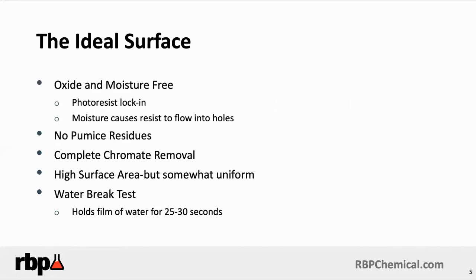Now, what is the ideal surface? The ideal surface to get good photoresist adhesion has got to be clean, right? Clean virgin surface, oxide-free, moisture-free, no residues left on the surface. We talked about chromate removal, and we're going to talk about how important it is. Chromate is what's put on the copper foil by the copper manufacturer to minimize or prevent oxidation when they ship you the copper. Well, that chromate has got to be removed. And where a lot of people make a mistake is they don't remove the chromate first, prior to going into some of the other aspects of the surface preparation process, whether it be pumice scrub or other chemical cleaning. So I always recommend as a first step, remove the chromate with an acidic mix of chemistry with some surfactants in there that will give you a cleaner copper surface, so you can remove some of the organic residues from the copper surface prior to going into the next step.